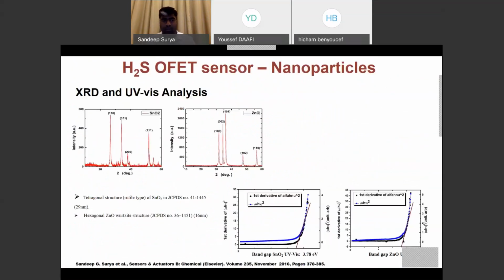In order to first confirm that the materials synthesized by green synthesis are indeed tin oxide and zinc oxide, we did XRD, UV, and even EDAX. From the XRD, the peaks correspond to tin oxide in this case and zinc oxide in this case. They are also really crystalline in nature. From the Scherrer equation, we were able to estimate the crystallite size to be around 29 nanometers for tin oxide and 16 nanometers for zinc oxide.